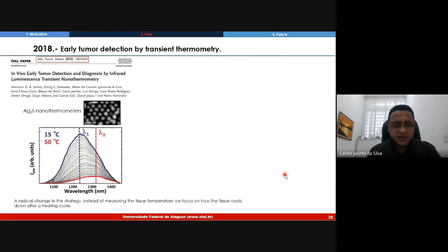In this, we investigate in vivo early tumor detection and diagnosis by infrared luminescence transient nanothermometry using silver sulfide nanocrystals. The idea is so simple. This material is very interesting. One of the most interesting materials because it's very small, more or less 4 nanometers, and it presents optical parameters depending on the temperature.